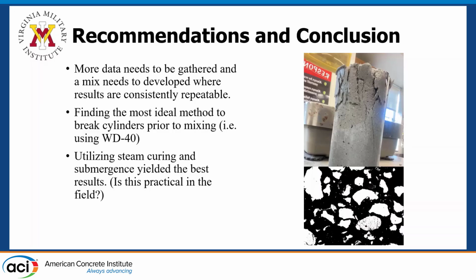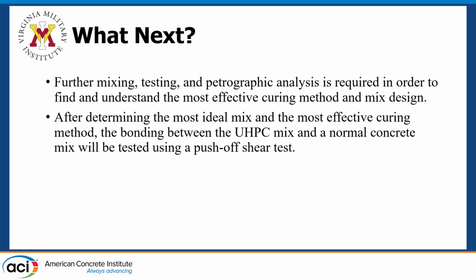Utilizing steam curing and submergence yielded the best results. However, is this practical in the field? In a perfect precast world we could, but on a site where we're mixing concrete, ready mix right there with a truck, it's very, very difficult to put things into a steam/submergence apparatus. So what next? Further mixing, testing, and petrographic analysis is required in order to find and understand the most effective curing method and design. So we still have to work on that.